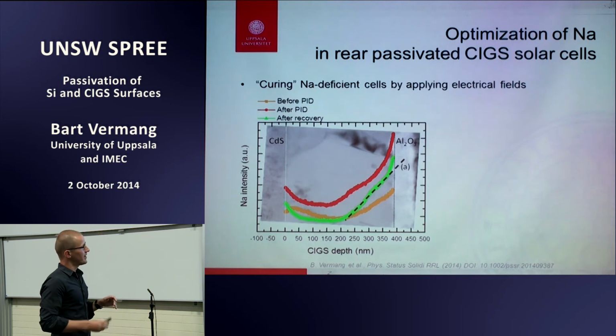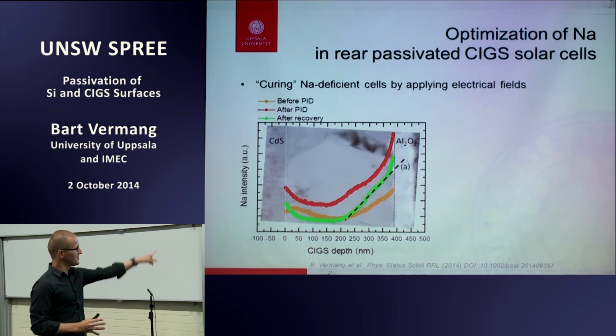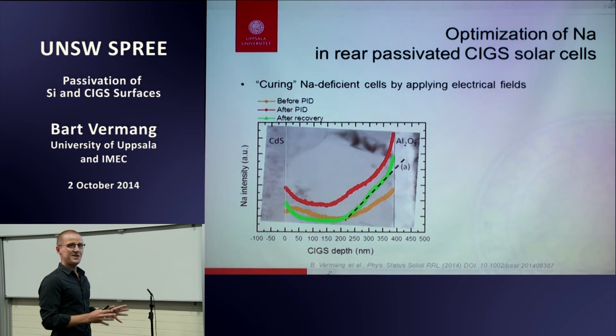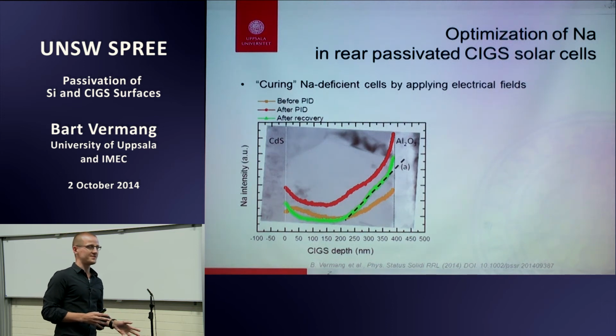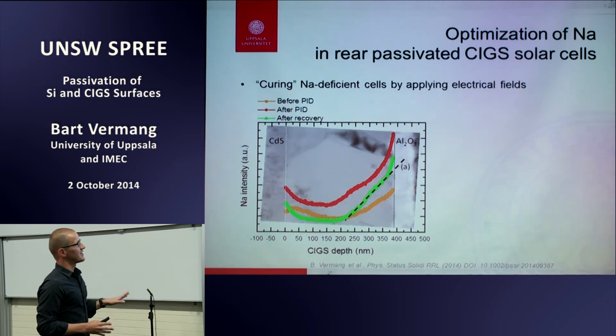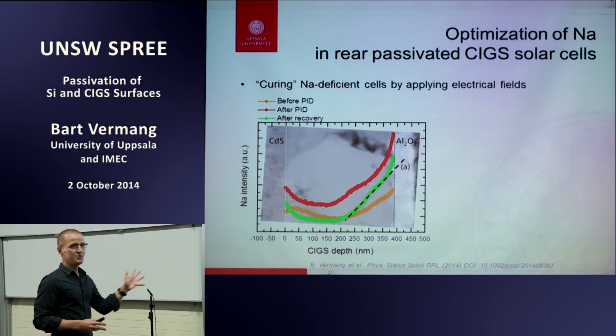But we found a way by applying field effects, because we are using PID, potential-induced degradation, that we can move sodium inside the CIGS layer and increase to the red curve. And if we change the polarity of the electric field, we take out the sodium again, and only the sodium that we want to be there remains, which is the green curve. And this way, we have been optimizing our rear-passivated cells. So if you look at our publications, for the best cells, we use this kind of tricks.